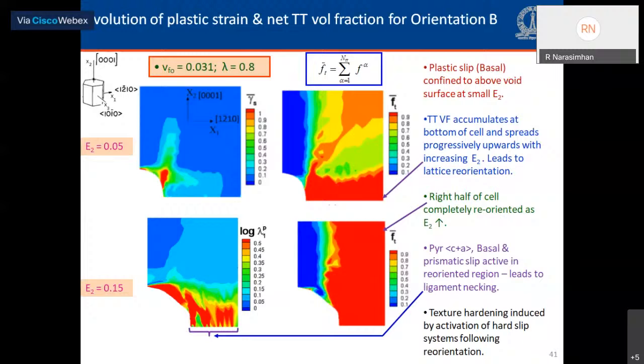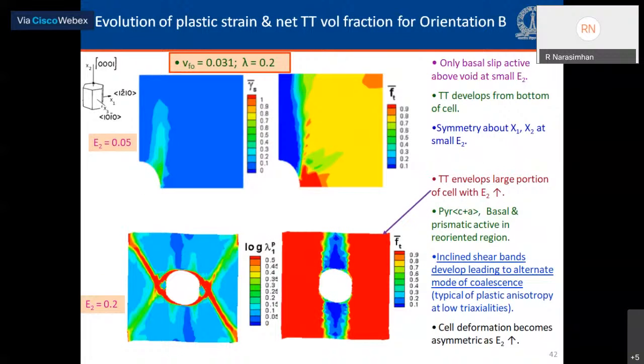Now, once that happens, the lattice reorients and it triggers additional slip activity, particularly the hard slip system like pyramidal C plus A gets triggered. And you can see that evident in the left side bottom image, where it has formed slip contours, plastic strain contours on the transverse ligament. And ultimately necking of the transverse ligament takes place. And one of the features of this is that it leads to a lot of texture hardening, as we will see from load displacement plots.